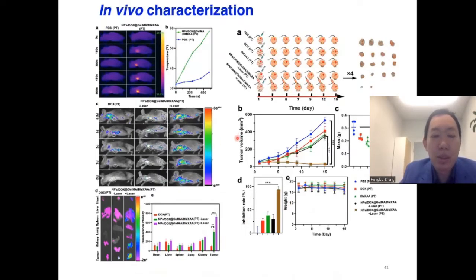And then we injected this hydrogel, microgel-based particles locally into the tumor. So with one dose, they can sustain release the drug for a very long time. And interestingly, we found that we can clearly reduce the systemic side effect of the drug dose. And also, even with 25 times less total drug dosed compared to this tail injection, we can have a better tumor inhibition effect. So this method is very effective.